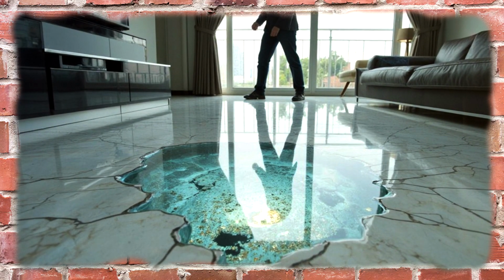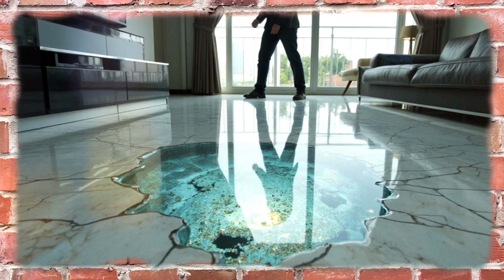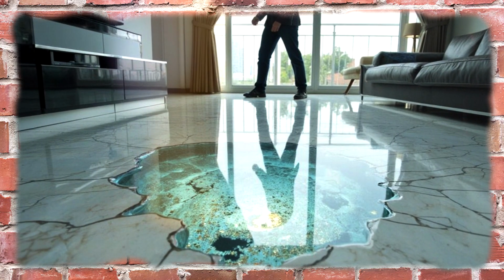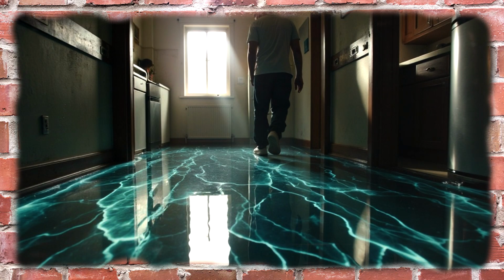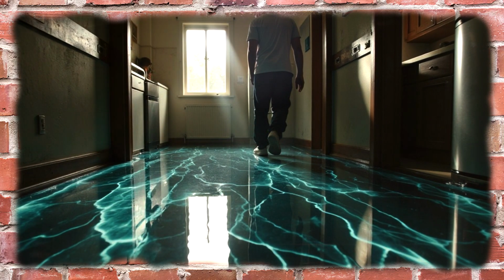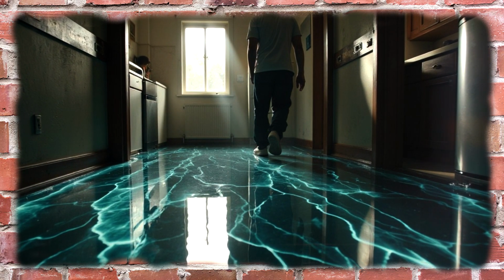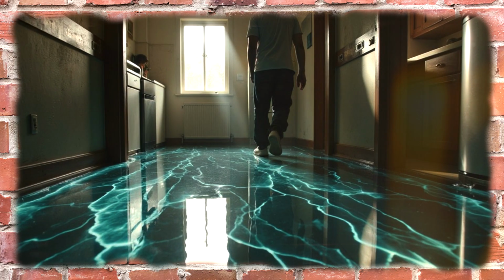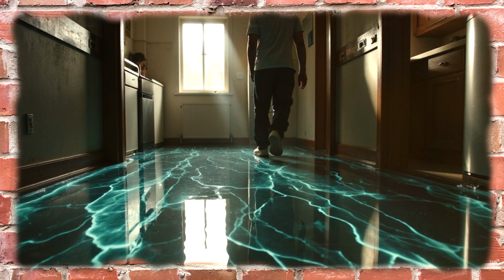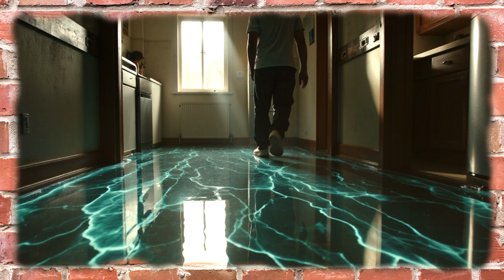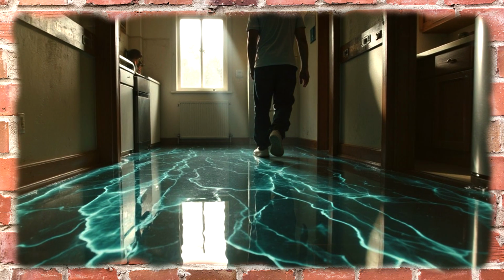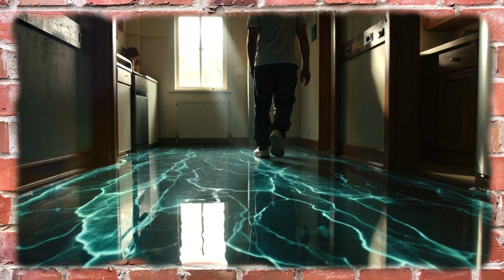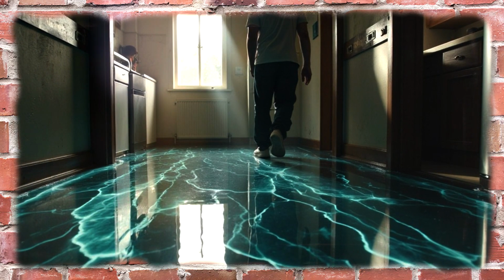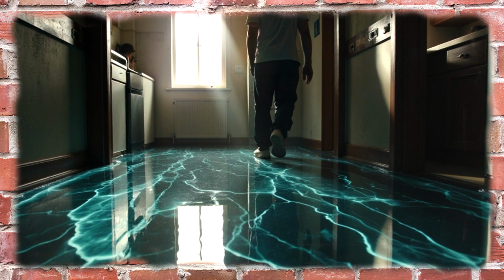An epoxy floor reaches its full strength not all at once, and even if it is hard to the touch, the internal bonds continue to form for another 28 days. During this period, you cannot place heavy furniture or move it, or use aggressive cleaning agents. In Dublin, a restaurant opened its hall 3 days after pouring, and the very first batch of chairs placed on metal legs without felt pads left micro-cracks that, over time, turned into a grid of cracks.